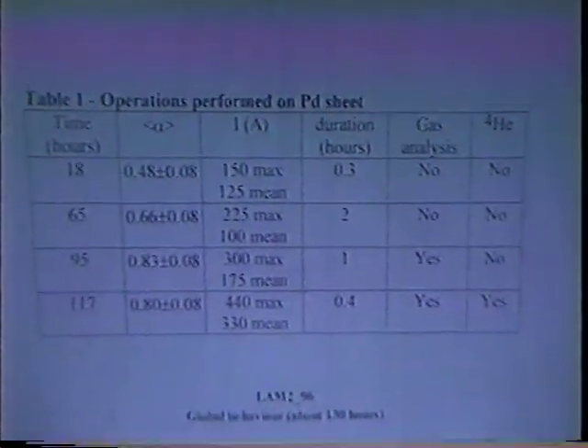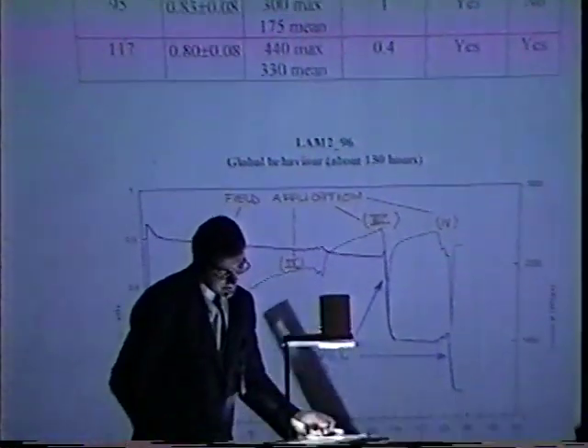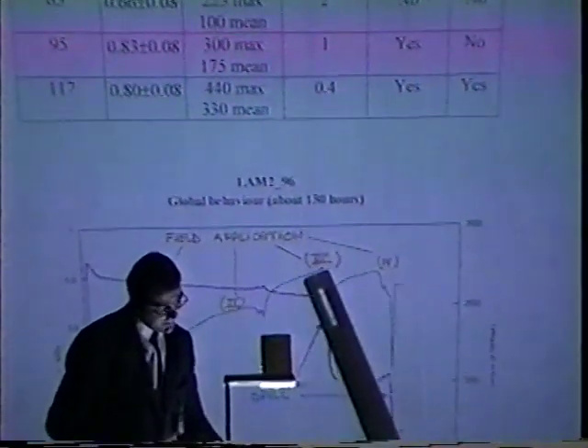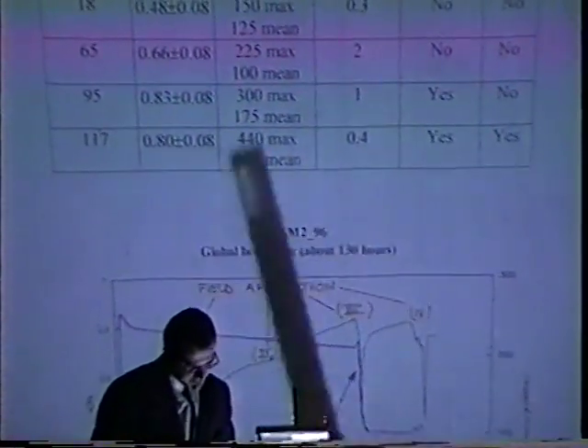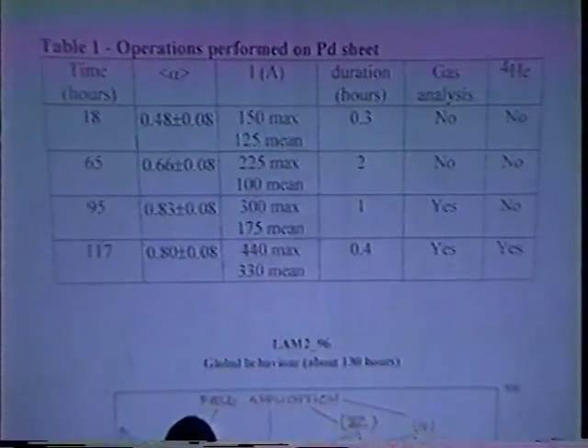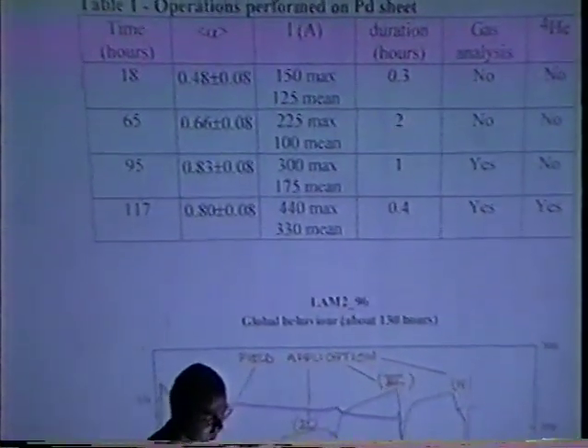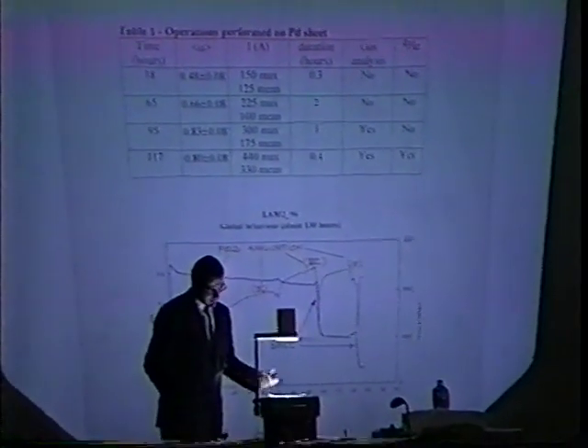Going back to this global behavior, we performed two applications of electrical field without doing any gas analysis, 1 and 2. After that we performed an application of electrical field corresponding to a maximum current of 300 amperes, with a corresponding mean value of 175 amperes. In this case, helium-4 analysis was performed on the gas spilled from the cell at about 1 bar, but we had no evidence of helium-4 presence in this case. At least we didn't find helium-4 over 0.5 per thousand of the analyzed gas.